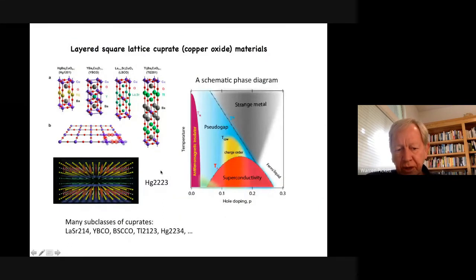Okay, this is the cuprate superconductor, the same structures. And there's a really interesting phase diagram here of temperature on this axis, and this is hole doping in the material, alloying somehow, usually replacing one cation with another cation that has a different valence. But here's superconductivity and an antiferromagnetic state over here before you dope it, and a pseudo gap region, which is still being investigated a lot. It has been investigated a lot. Strange metal phase here, and then over here is a normal metal phase once you get far overdoped. That's the interest in cuprate superconductivity, and that continues still.